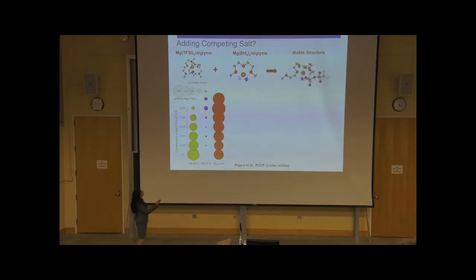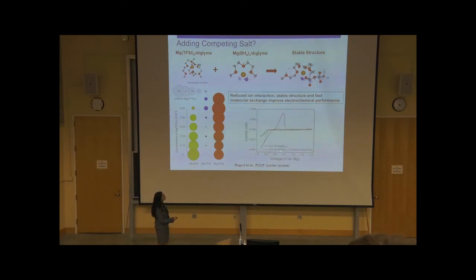And what we found is that by mixing these two competing salts, we are actually forming some sort of stable structures in the solution, which result in enhanced electrochemical performance of this mixed electrolyte as compared to the single salt by itself. So basically, by simply changing the molecular level properties of electrolytes by reducing this strong cation interaction, there are ways of how we can actually enhance the electrochemical performance of electrolytes.